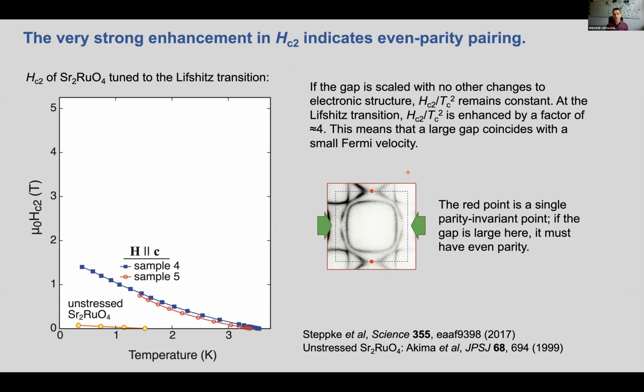I mean, I can't give an absolute 100% certain answer to that question. My colleagues Thomas Scaffidi and Steve Simon have done weak coupling calculations for various order parameters, comparing even and odd parity order parameters. And they calculate the gap within this weak coupling model for all of the Fermi surfaces. And they confirm in their calculation that the even parity order parameters have this strong enhancement in Hc2 over Tc squared, while the odd parity order parameters do not. And I think this extreme rise in Hc2 as well.